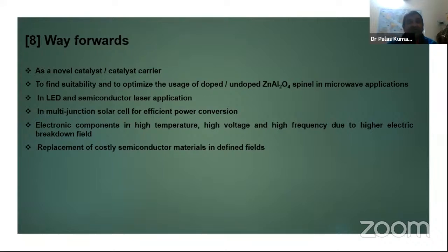But if we use a wide band gap material like gallium nitride, which is very, very costly, using this multi-junction component, the power conversion efficiency will automatically grow to 80%. So a huge jump, but the cost is very high. But now, if we replace gallium nitride with titanium doped zinc aluminate, you know very well gallium nitride is very, very costly.